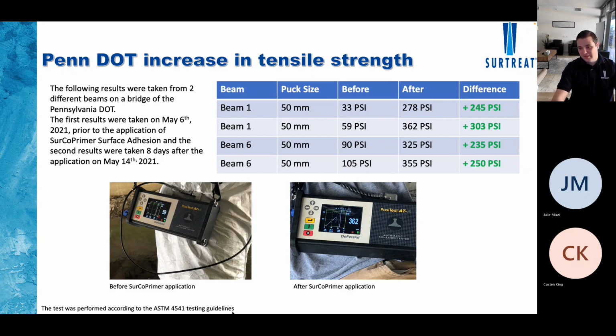Then this is a more recent case study. This was last year, where PennDOT had a bridge that needed FRP reinforcement. For those of you who don't know what that is, FRP reinforcement is a surface applied structural reinforcement that adds capacity to any structure. So if you need to increase the loading capacity, you can apply FRP, but FRP has certain parameters. You cannot install FRP on a structure that has under 100 psi pull-off strength. So you need to ensure that the structure you're repairing with FRP doesn't have corrosion, because if it does, it will still deteriorate.